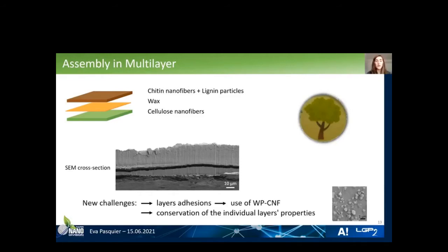However, when we did the SEM cross-section, you can see that there is a big crack in the middle, and this happened during the preparation of the sample for SEM. But it means that the samples are quite brittle, and this is due to the wax layer in the middle. One way to improve this would be to use the wax with the CNF, so that maybe we have some reinforcement from the CNF in the wax layer. This is ongoing work, so we still need to do it. And also we need to check if we have conservation of the individual layer properties in this multi-layer.